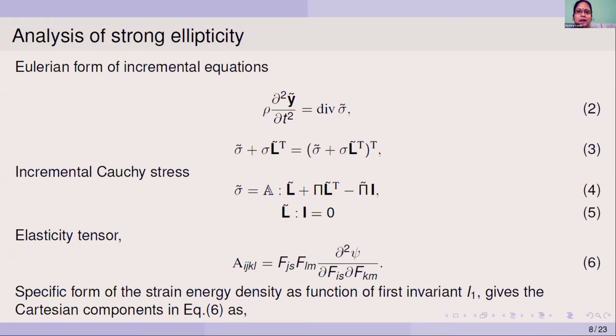Here y tilde is the incremental displacement vector which is superimposed onto the displacement y, and this sigma tilde is the incremental Cauchy stress tensor, and this equation 3 gives the balance of angular momentum. Here L tilde is the incremental velocity gradient. And this incremental Cauchy stress tensor for an incompressible material is given by this equation 4. Here this A is the fourth order elasticity tensor, and these two terms account for the incompressibility. This pi is the Lagrange multiplier, and this pi tilde is the incremental Lagrange multiplier. And this equation 5 is the incompressibility condition in its incremental form.